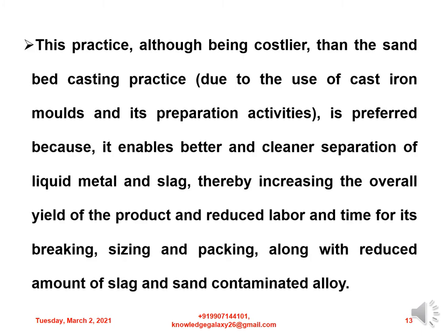This practice, although costlier than the sand bed casting practice due to the use of cast iron molds and their preparation activities, is preferred because it enables better and cleaner separation of liquid metal and slag, thereby increasing the overall yield of the product and reducing labor and time for breaking, sizing and packing, along with a reduced amount of slag and sand contaminated alloy.